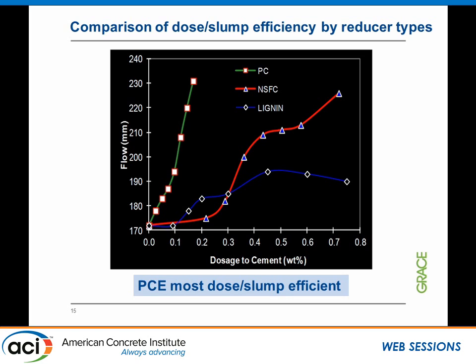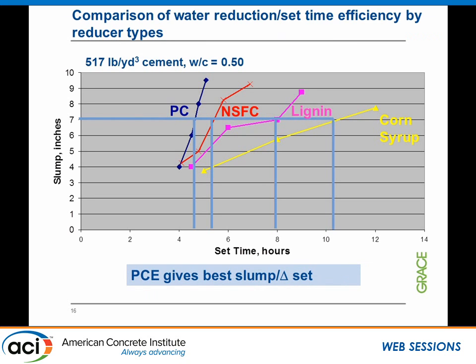With the introduction of polycarboxylate, what we realize is we can get to that same level of water reduction or flow with much less amount of chemical being used. So the number 1 criterion of how do we use less chemicals to get the most flow is demonstrated in here by the use of polycarboxylates. And then if you look at a mix where you have the set time versus the slump, with the use of corn syrup, lignin, naphthalene sulfonate, and polycarboxylate, definitely for the polycarboxylate, we once again see that it gives you the best slump with the least amount of set time.